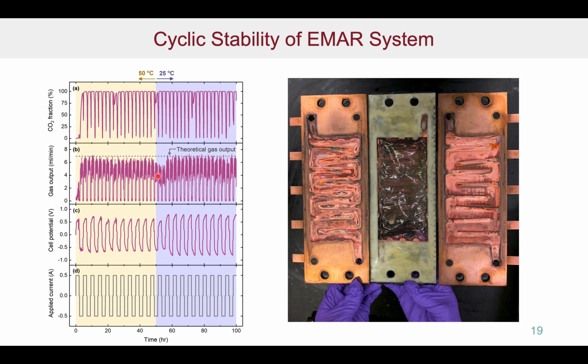This shows you the kind of results that we can get. In particular, what we're interested in is the gas output product. You can see that generally we're getting around 100% CO2 coming off our column. And the gas output rate is very close to the theoretical gas output rate, which is controlled by the current itself. This is the applied current, and that determines the rate at which the CO2 is released, because that determines the rate at which copper is released. And then we get the cell potential as shown here.